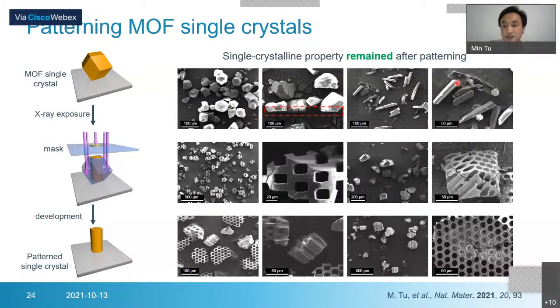And we can see here is some rod, but unfortunately it doesn't stand on the surface, it kind of collapses on the surface. And we can also make some periodical holes on the MOF crystals. And a very interesting property is when we bring these single crystals to do single crystal XRD measurement, we can also solve the structure. So it still remains single crystalline. We didn't have any damage on this unexposed area.